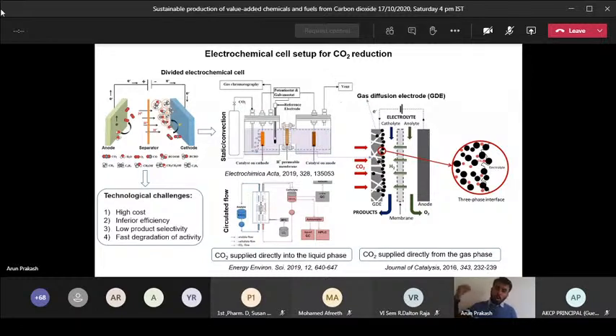Also, some products will be formed at the counter electrode as well. Pt is the counter electrode. You can use a graphite counter electrode if you are using an acidic pH. So you have to use these best practices for CO2 reduction. The main purpose of the proton permeable membrane is that protons will be transported from one compartment to the other, and even if hydrogen is evolved at the counter electrode, it will not dominate your CO2 reduction, though it will affect your efficiency. So this is the purpose of the divided cell. In the case of a single cell, you don't have a separator, and the working, reference and counter electrodes are all present in the same cell.